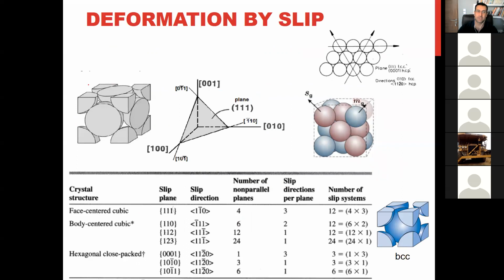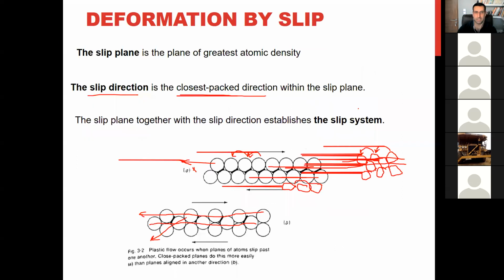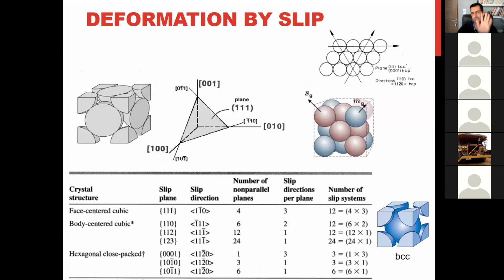In FCC crystal, this is an FCC crystal, as we see here. This is close packed. Here you can see from above. This close packed plane is this 1, 1, 1. You see? This is the close packed plane, and just this plane has 3 directions inside. One is this, another is here. Sorry, I cannot draw it like this. Here you can see just these 3 directions for FCC crystal, and we have such a plane, 4 planes in the FCC crystal.